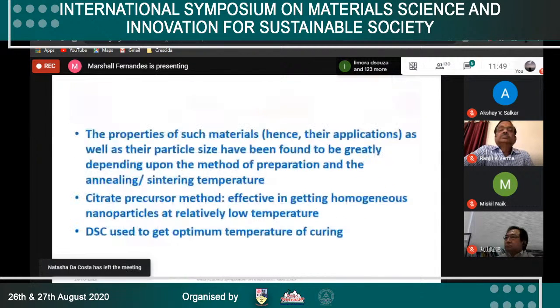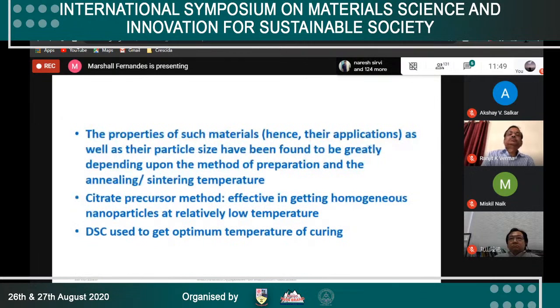The properties of these materials, the ferrites, depend upon the way these ferrites are prepared. The method of preparation determines their particle size. So what we have done in these 4 cases, we prepared a citrate precursor and then annealed it. In some cases, sintering was also done, heating it for a certain period, 3 hours or so, at a particular temperature, 600 or 500, and then suddenly cooling it down to ice temperature, heat quenching. So annealing, sintering, and heat quenching.